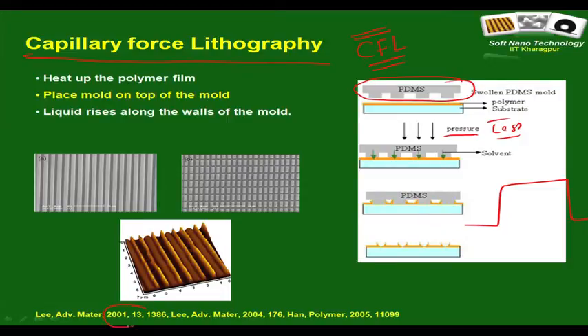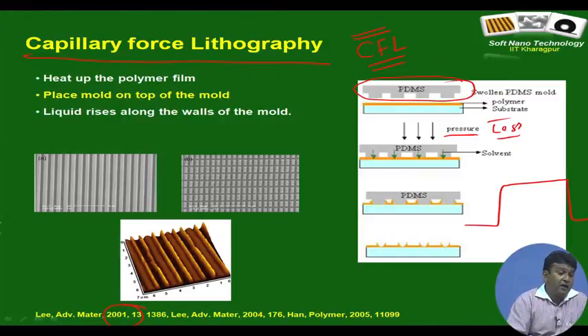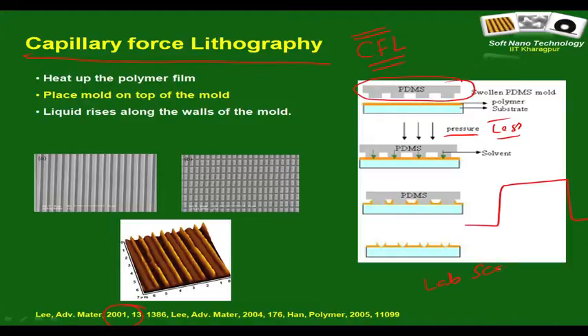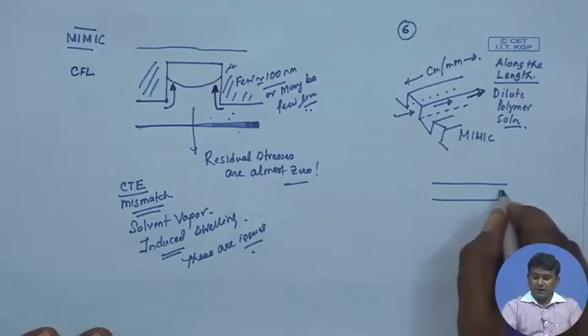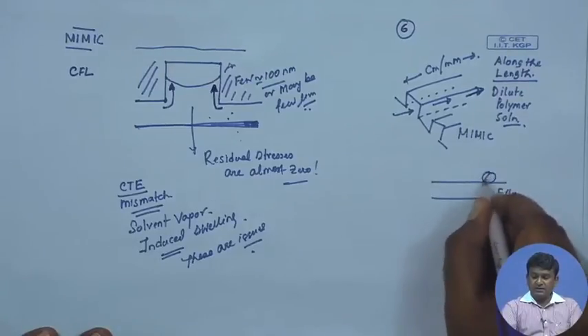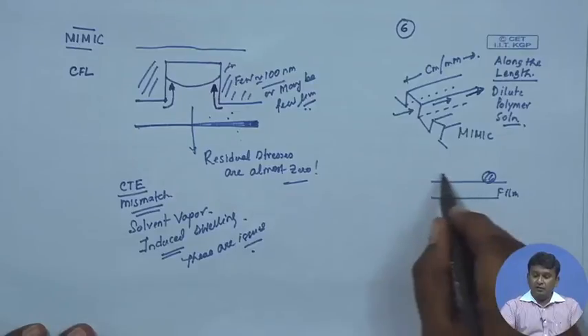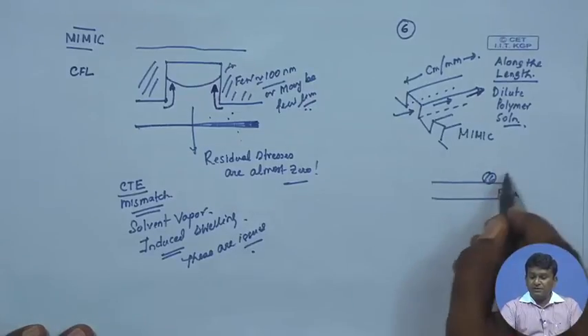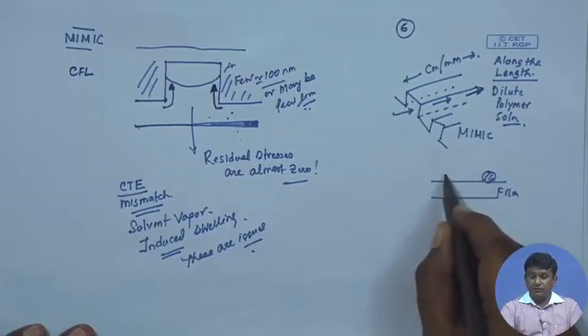It was developed around early 2000. It is indeed a very popular nano patterning technique, and a lot of people implement it at lab scale, because unlike nano imprint lithography, it almost requires nothing. You do not even require a clean room, because unlike NIL, you are not using a rigid stamp. So, even if there are some dust particles here and there, what will happen? Suppose I am talking about a very practical situation. You have a film which is dusty, here is a dust particle. As I told, if you want to bring in a NIL stamp, it will simply break, because you are applying a pressure, it will form a couple, etc.